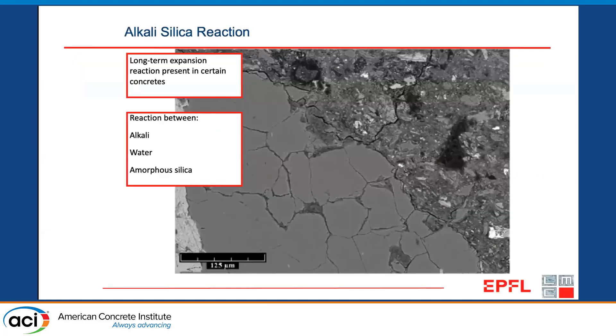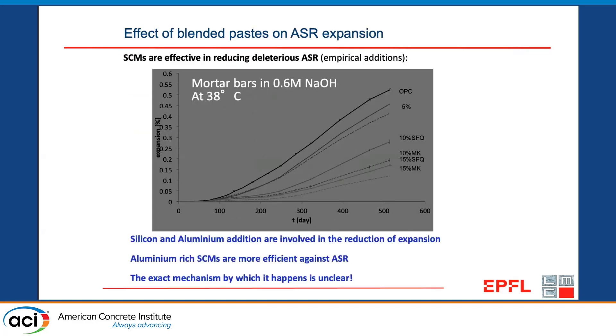The starting point — I think everybody knows what ASR is. This is a nice picture of the kind of aggregates we have in Switzerland. They're often pretty much quartz, which everybody reckons is an unreactive material, but you get the reaction going along grain boundaries because any grain boundary has amorphous material more vulnerable to attack. The starting point for our work was the anecdotal observation that SCMs with aluminum were better at suppressing ASR than ones with just silica.